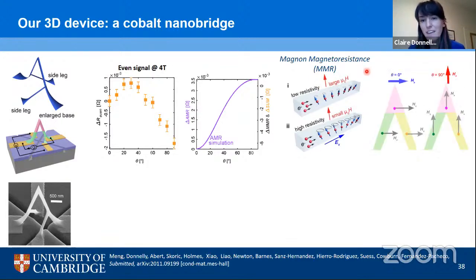And now you may think, in a 3D structure, okay, we're applying the same four Teslas at different directions, but it turns out that the 3D structure has a very strong influence on the magnon magnetoresistance because of the demagnetizing field, so the magnetostatic energy of our structures. Specifically, when we look at the demag field of our structures, because we have these non-collinear regions of the bridge, we have a strong influence on the resulting effective field, so the total magnetic field that is felt by the magnons,